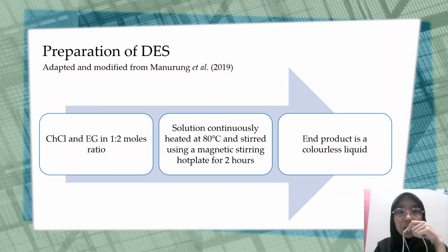A 1 to 2 mole ratio of choline chloride and ethylene glycol DES was prepared by continuous heating and stirring at 80 degrees Celsius for 2 hours until a colorless liquid was obtained.